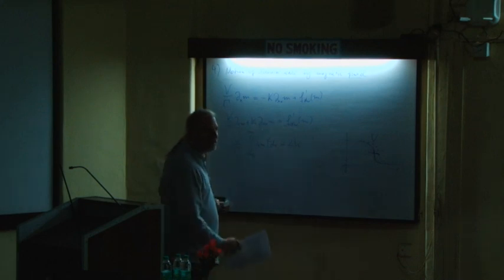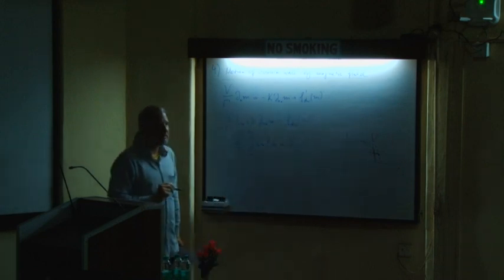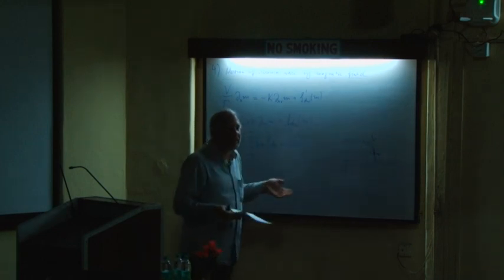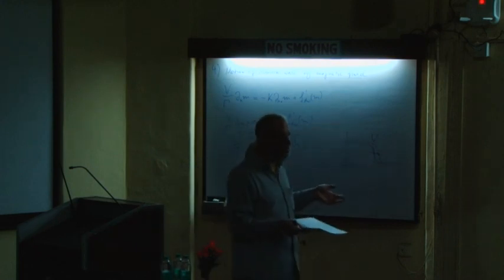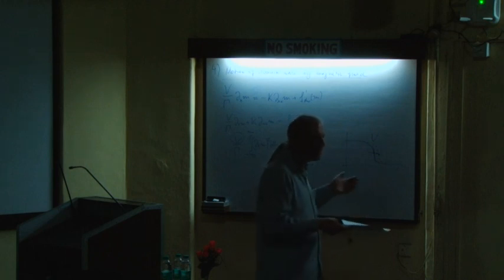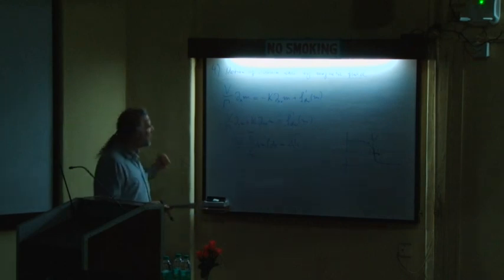Okay, we already have obtained a very important relation. You see, the velocity is proportional to the magnetic field. Which is kind of intuitive, because if there is no magnetic field, there is no motion. And if you put a small magnetic field, this is like a small perturbation, so it's quite reasonable that the velocity to first order must be proportional to the magnetic field. Now the question is, what is the constant of proportionality?